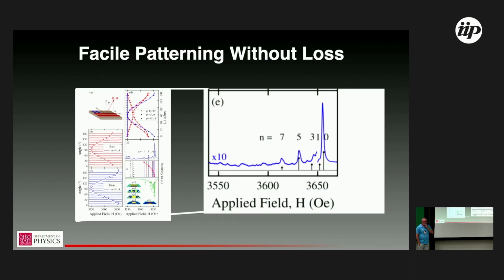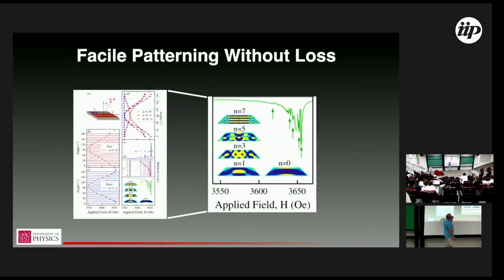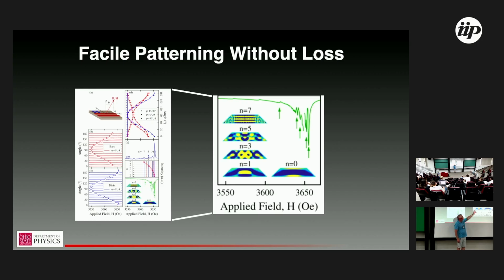Quick clarification. The odd harmonic modes, does that rely on any understanding of the surface pinning? Yes. I should have said that. I was a little too glib. So an additional parameter we have to take into account to get the mu-max to work is that we can set these boundaries as either free or pinned, and that will shift the position of these resonances. And so when my student Andrew Franson did all this work, and it's beautiful work, but you want to nail down as many things as you can nail down.